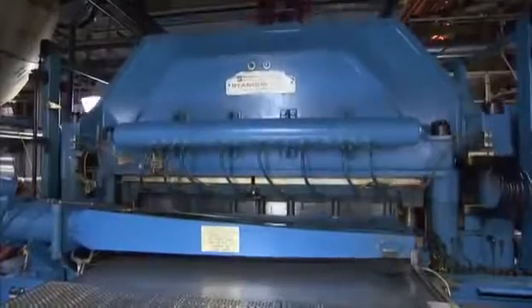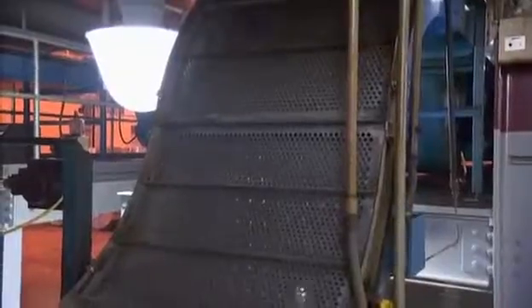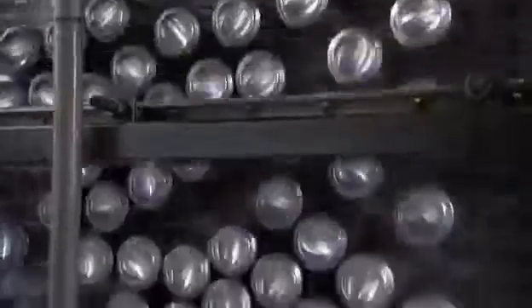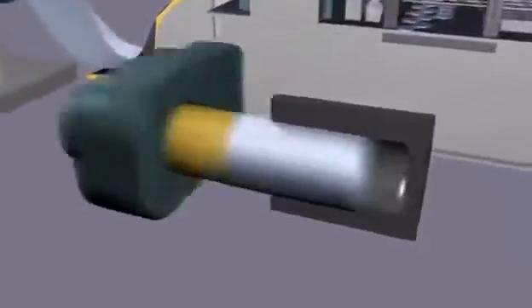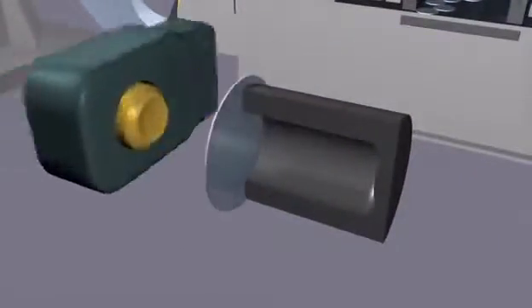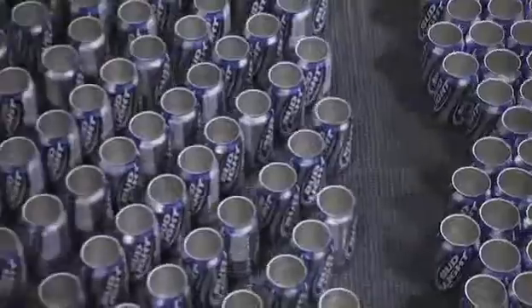Each tiny disc is then stretched to become a full 12-ounce beer can. Incredibly, aluminum can take this pounding without tearing or breaking. Because it's so ductile, it doesn't even need to be heated to take on a new form. It really allows the product to stay fresher than most packaging materials, and that's the beauty of the aluminum. The stretching is done by a cylinder press that slams into the disc. The force of the impact draws the metal out an incredible 400 times its original height and creates a 12-ounce container. But it still doesn't have a top.